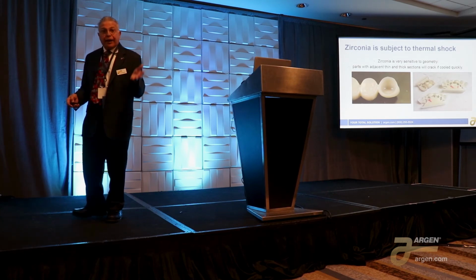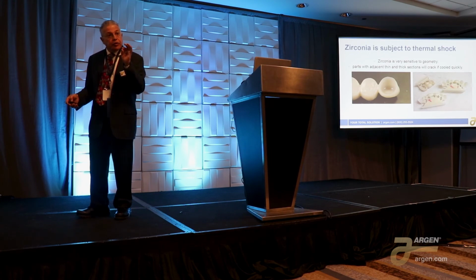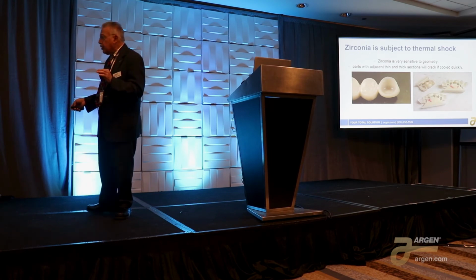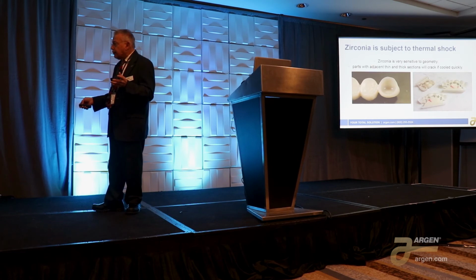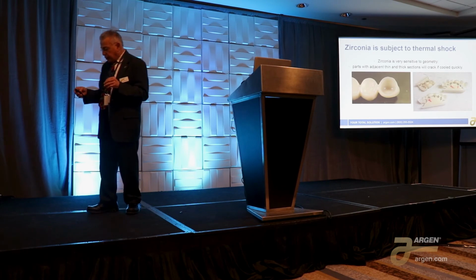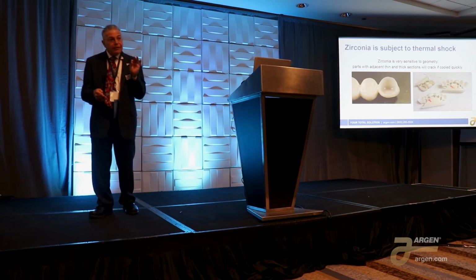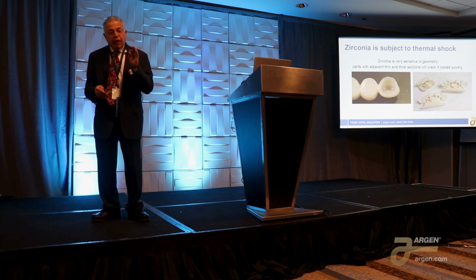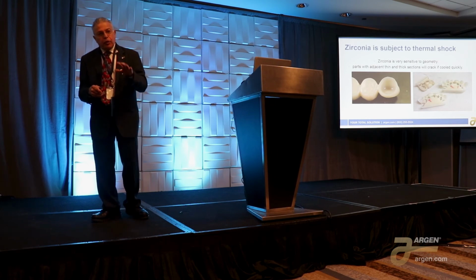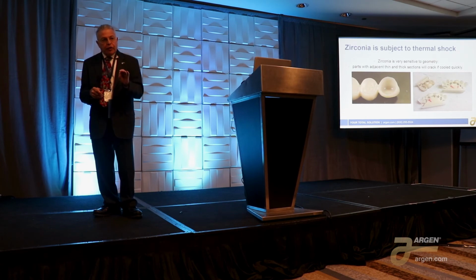But you also have a thick and thin situation when you try and use connectors that are just too thin. And here you have that situation. There's a variety of different bridges, and they did the right thing by using these supports. However, the connectors that they used were too thin. And because they're too thin, they have a thin next to a thick and a crack. And some of the cracks extended into the restoration, unfortunately. So just be aware, thick to thin is difficult. Don't try and stuff 52 units in a disc. Use the larger diameter supports. That'll solve this problem.